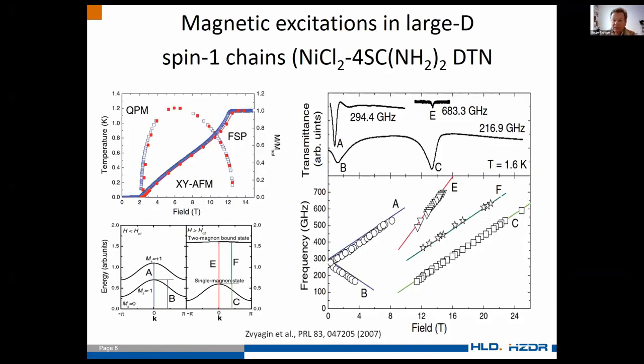So another picture again, so this is a so-called magnetic excitation in large D spin one chains, DTN. And again, if you look at the phase diagram, you would end up with three different phases. The high magnetic field phase is this fully spin polarized phase. So at low field, we have a quantum paramagnetic state when the gap is open, and this gap is because of very big zero field splitting because of nickel. And at intermediate field range, we have some states which can be described using Bose-Einstein condensation formalism. So this is the BEC phase.